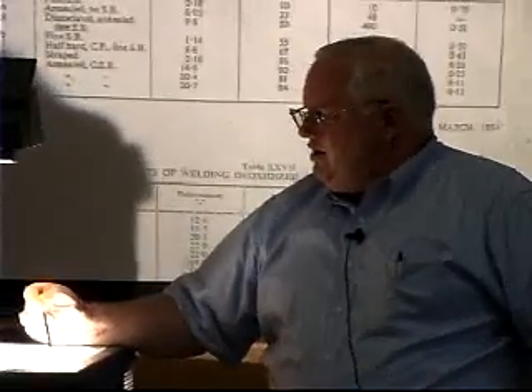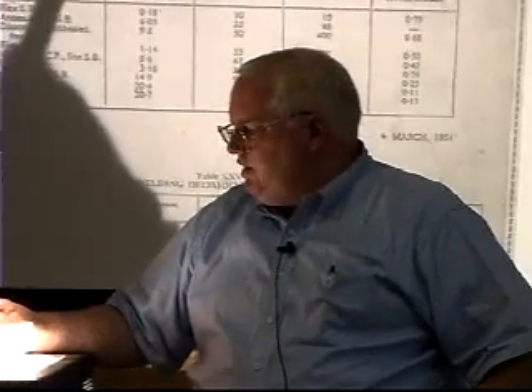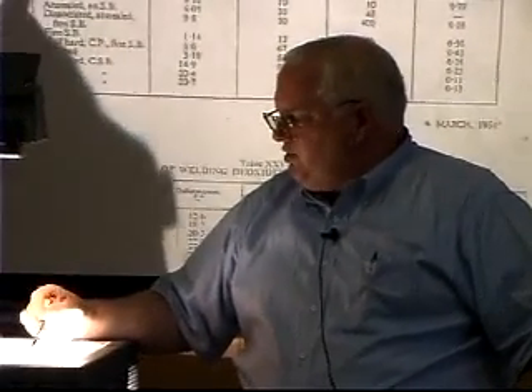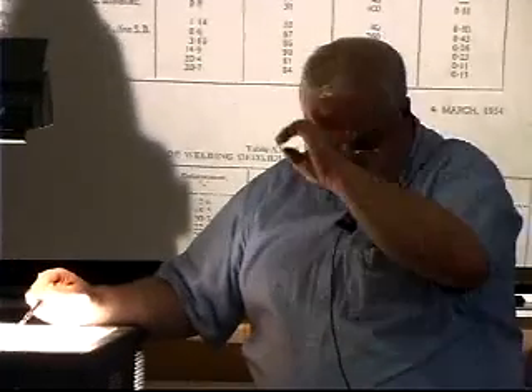They basically took the oxide to metal hardness ratio, and they deformed two pieces of material by different amounts. This is percent deformation: 20%, 40%, 60, up to, you can't get to 100%, but you can approach it. And they found with less than 20% deformation, indium metal was the easiest thing to cold weld.